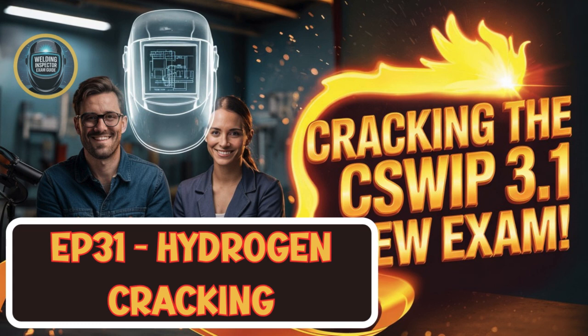Right, you mentioned a specific danger zone. That's the heat-affected zone, the HAZ. It's the metal right next to the weld that didn't melt but got hot enough for its internal structure, its microstructure, to change. That's the prime spot for HICC. Mostly there, but not always. Mostly, yeah. But you can sometimes find these cracks in the weld metal itself, too.